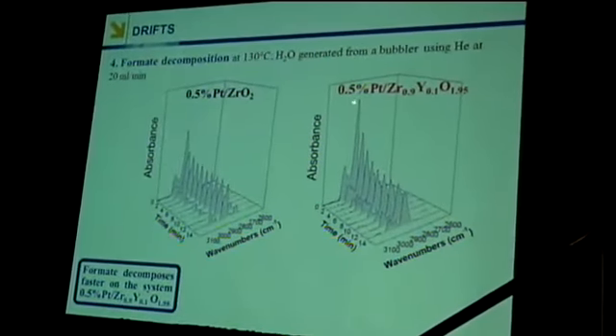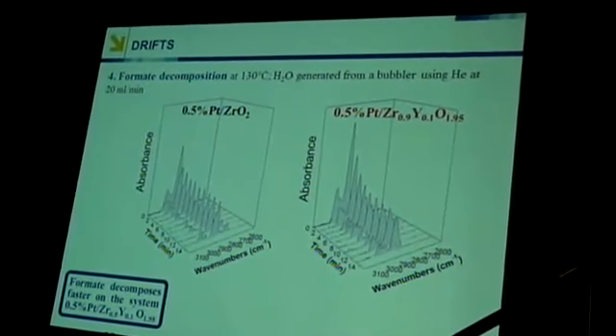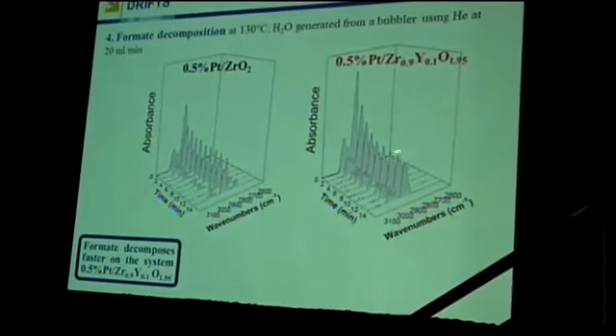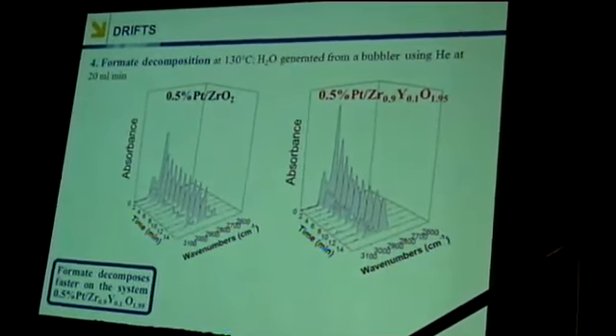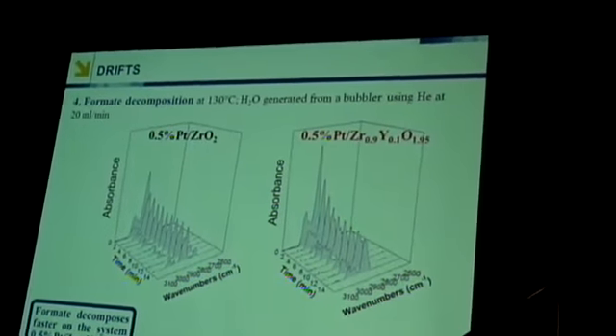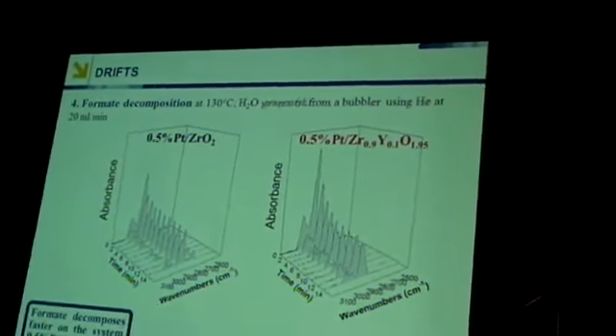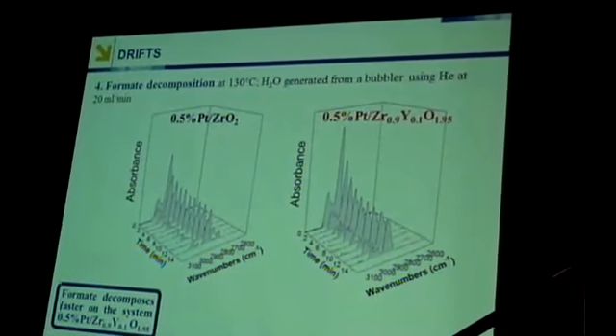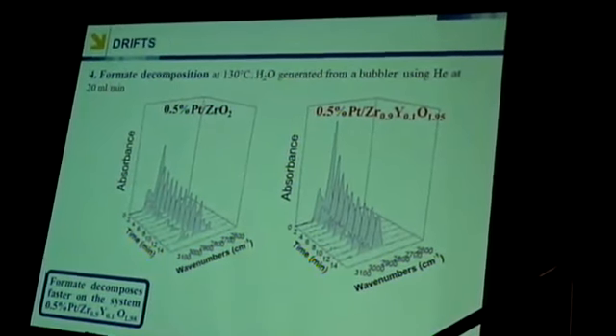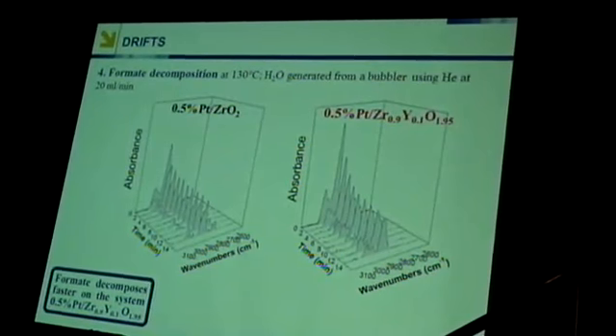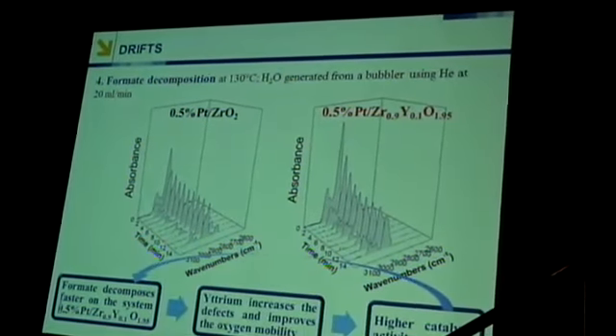And of course, we have more rapid formate decomposition when formate is at the interface. So the formate here is most likely on the support, away from the platinum particles, and has to diffuse to the platinum in order to decompose. So this faster rate suggests perhaps an improvement in the oxygen mobility, surface oxygen of the support, resulting in a higher rate.